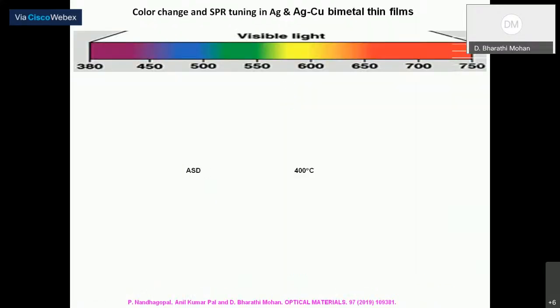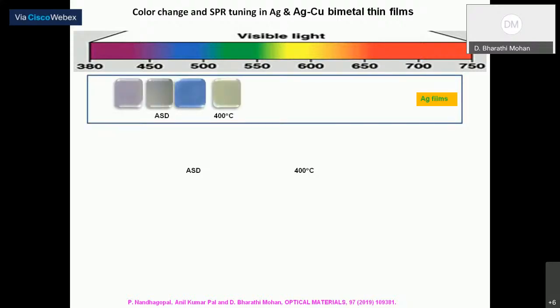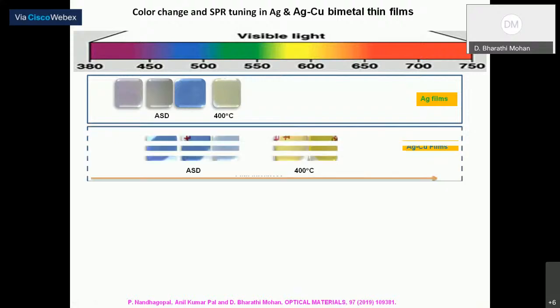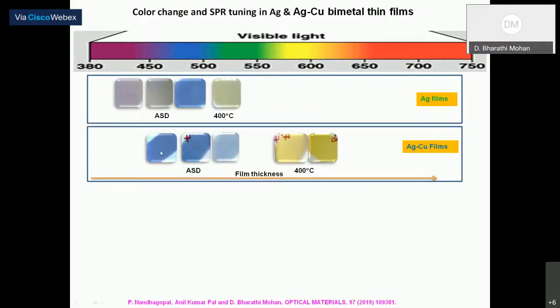Now, we also studied some of the color change and SPR tuning in both silver and silver copper bimetal thin films. And we know the visible light varies from 380 to 750 nanometer. The physical appearance of the films has been photographed for silver thin films, and you can see the as-deposited silver film starts with pink in color. As you increase the film thickness, it goes to dark blue. Then, when you anneal the same film at 400 degrees Celsius, it approaches green color. In the case of silver copper bimetal thin film, you can see initially it starts with blue color and then it goes up to bright yellow.